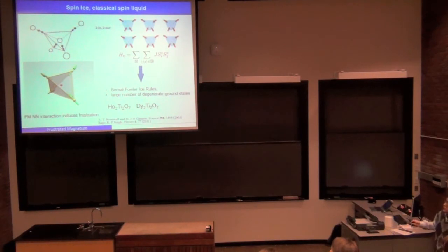And there are materials that show this interesting structure, for example, holmium titanate and dysprosium titanate. For those two materials, the rare earth ions are very classical objects because the spins are very big. And they are very anisotropic. The crystal field in this material limits the spins to point either into the tetrahedron or out of the tetrahedron. So it's really a two-state system for the spin, and the effective interaction between the spins is ferromagnetic.